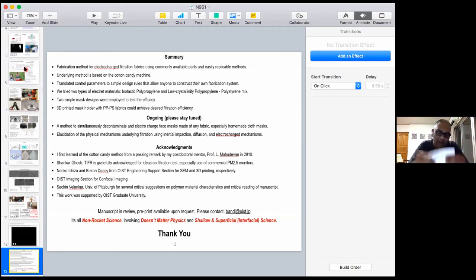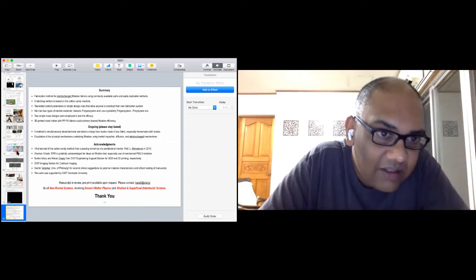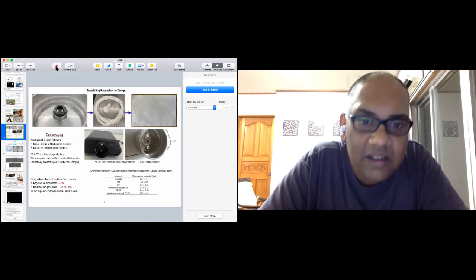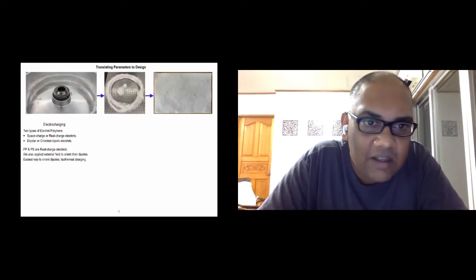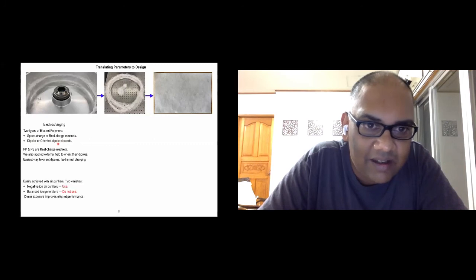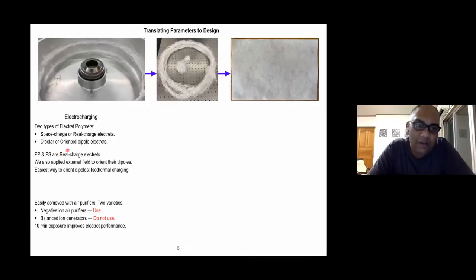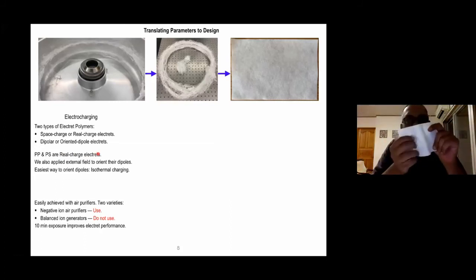That's one test I've been doing, and it is still ongoing. The first layers we made were around April 7th, and I've been testing the layers every day for the charge. In this slide, I showed you that there is the real charge electret and the oriented dipole electret, right? The materials I used fall under the real charge. That means they have embedded charges in them that do not die out. So you can leave it for months and it won't die out.